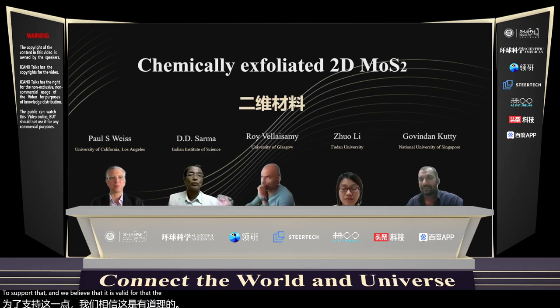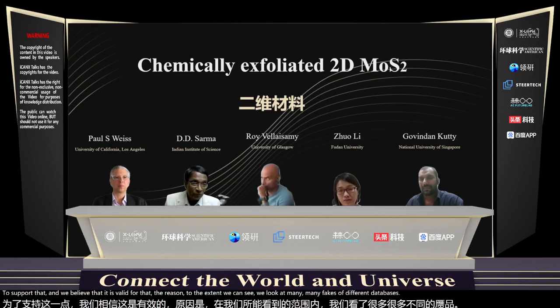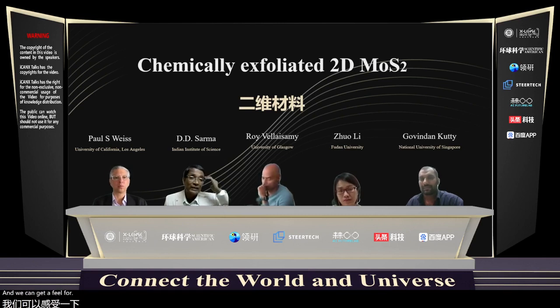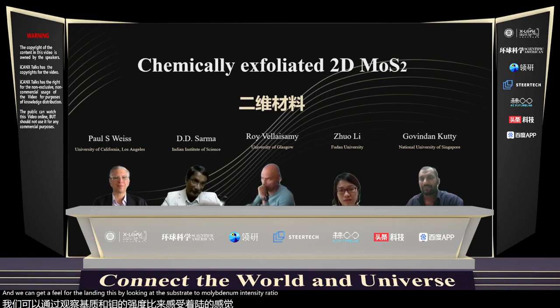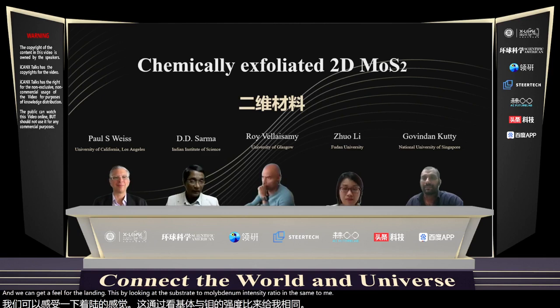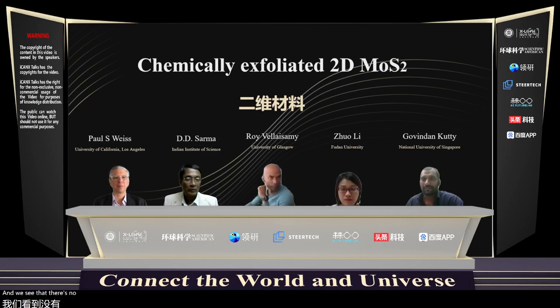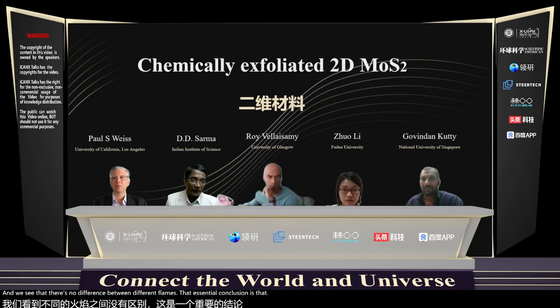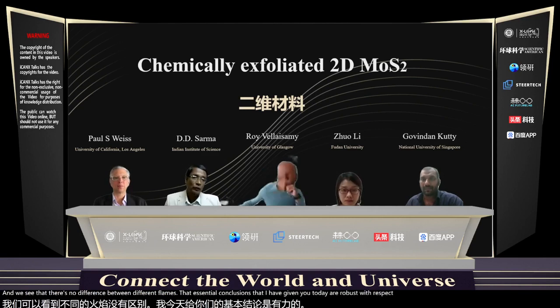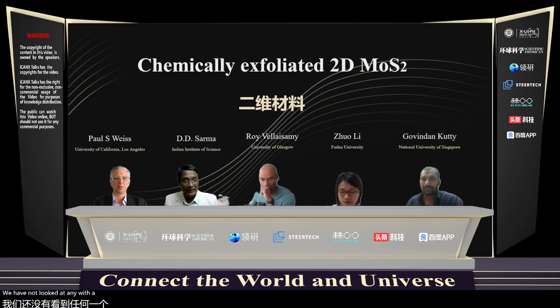To the extent we can say, we looked at many, many flakes with different layer thicknesses. We can get a feel for the layer thickness by looking at the substrate to molybdenum intensity ratio in the same technique. And we see that there's no difference between different flakes. The essential conclusions that I have given today are robust with respect to the layer thickness. We have not looked at any with a single layer, but that's a different question.